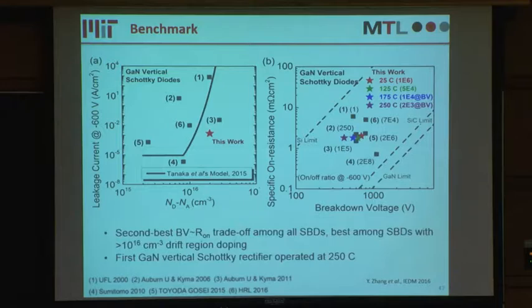Also, looking at the figure of merit of on-resistance versus breakdown voltage, we demonstrate the second best performance, and also demonstrate the first vertical gallium nitride Schottky rectifier that can operate at very high temperature, above 250 degrees C.